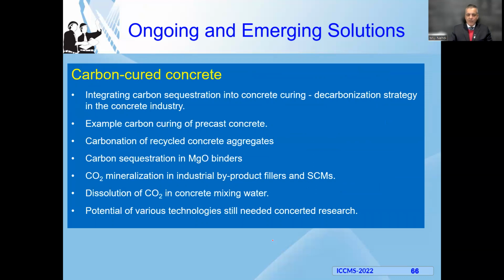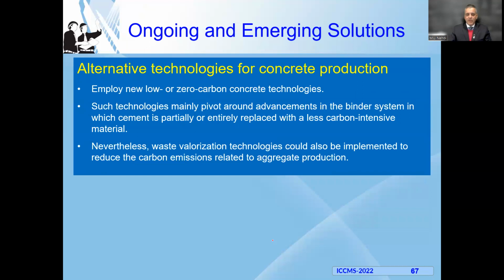So carbon sequestration is one thing, but the carbon use can go hand in hand. So integrating the carbon sequestration into concrete curing can be also part of the decarbonization strategy. The easiest way is probably to use it in the carbon curing of precast concrete, being simpler and easier because it's conducted in a controlled environment. The carbonation of recycled concrete aggregates, the sequestration of carbon in magnesium oxide binders, and the mineralization, maybe using the carbon along with some chemical solution that will produce things like, for example, aggregates. Dissolution of CO2, at least partly, in the concrete mixing water, and some other various potential applications. Some of them may emerge as innovations that probably we haven't thought about yet.